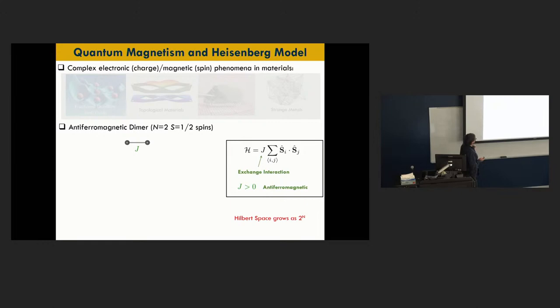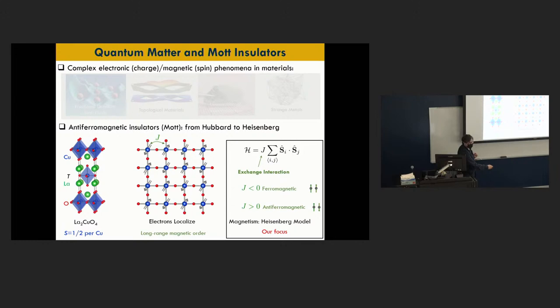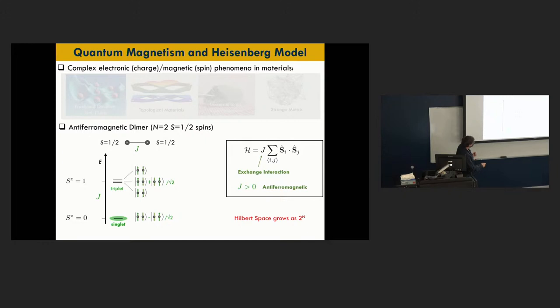And what you find is that, classically, you would say if I have an antiferromagnet, I'm going to put one spin up and one spin down. That's my ground state. But it turns out that quantum mechanically, this breaks rotation symmetry, so this is not a good ground state. A good ground state is actually a quantum superposition of spin up, down and down, up. And you have a singlet state, which corresponds to the quantum superposition of these two up-down and down-up states.